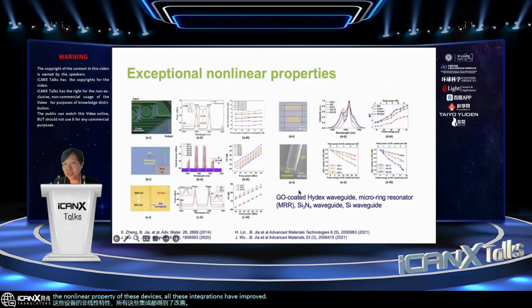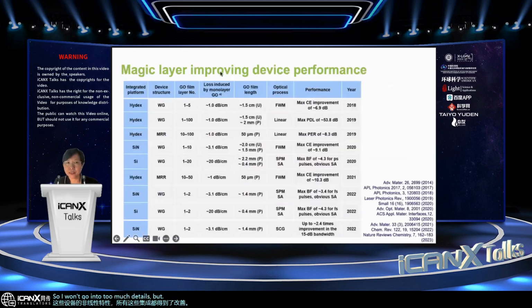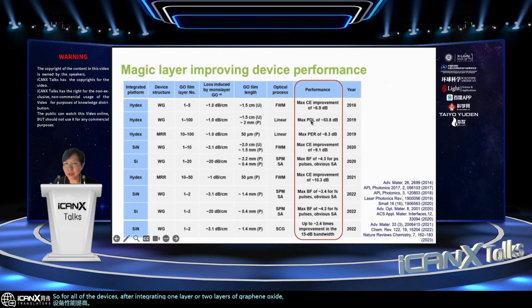So I won't go into too much detail, but if you're interested, you can have a look at the device performance increase. So for all of the devices, after integrating one layer or two layers of graphene oxide, you can see that the nonlinear conversion efficiency increased dramatically. Some of them even more than several tens of dB increase. So that means even with the existing architecture of the device, by only applying one or two layers of graphene oxide, you are able to dramatically improve the device performance.